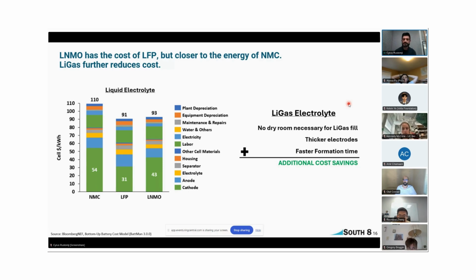You can understand this through the gassing process that occurs during your formation process. Those gases can block your electrode, and so you have to wait a very long time for those gases to diffuse out of your jelly roll to the surface to allow the electrolyte to re-wet that surface and continue to build that SEI layer. With the liquefied gas electrolyte under pressure, these gases are not really formed. If any of those molecules are formed, they just solubilize right into your electrolyte. And so you can accelerate your formation timing considerably, which is very nice.